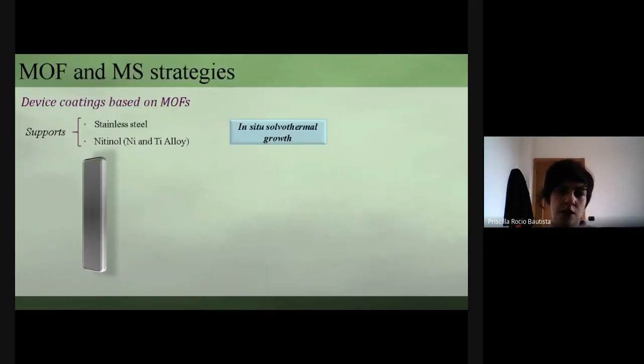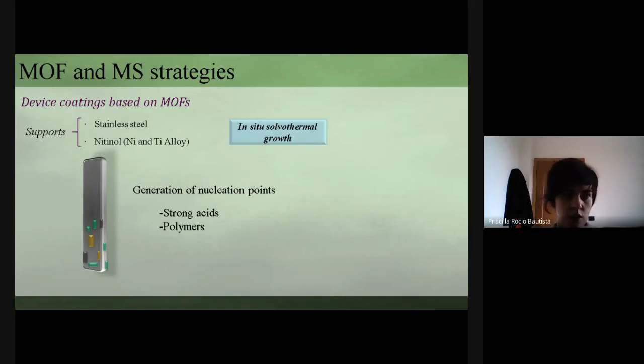How to obtain a device based on MOF to accomplish extraction techniques and mass spectrometry strategies? Our research group proposed an in situ solvothermal growth using two types of support, stainless steel and nitinol. During these procedures, there are two crucial steps. The first one is the generation of nucleation points onto the support to ensure a stronger link of the MOF on the final device. The easiest ways to obtain them are to subject the fiber to a strong acid treatment with hydrofluoric acid, piranha solution, or aqua regia, where the surface is directly damaged by the acid,